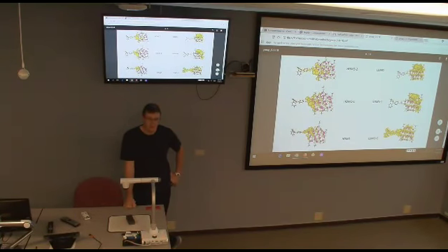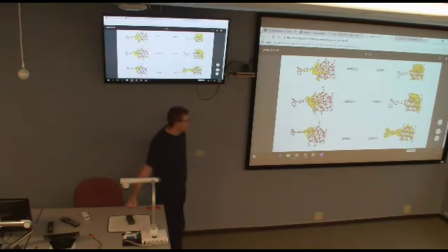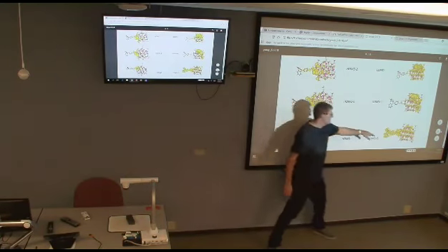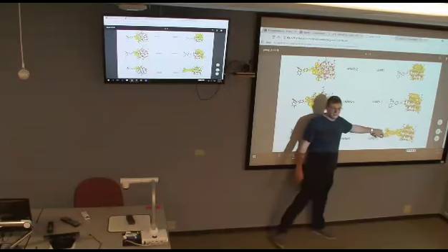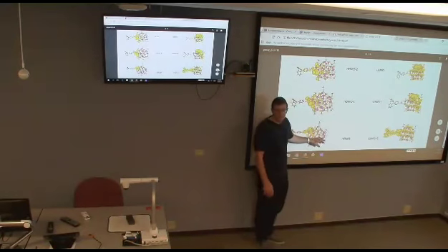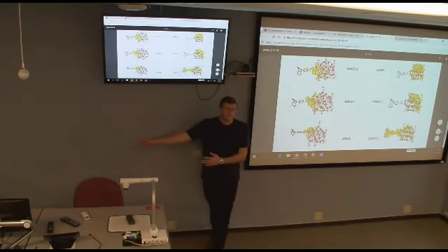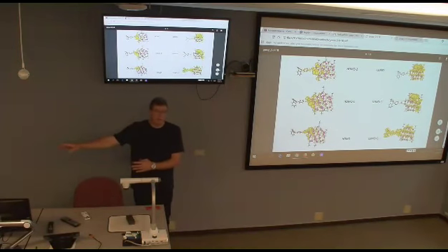Okay. Yeah, it provides some additional bias from a hole transport layer, or like the lead contact. But again, if you want to use it as a photocatalyst, I'm not sure if this molecule really can be used as a catalyst. Probably not. Yeah, because I mean, you'd rather see something like these types of delocalizations at the edge of the valence band, because then you're getting a large percentage of that charge out away from the quantum dot, where it's more likely to react with something coming in.